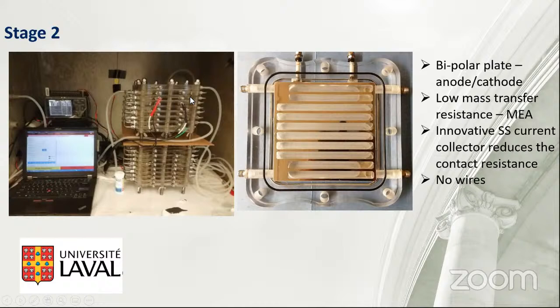This microbial fuel cell is basically inspired by the hydrogen fuel cell. It has a bipolar plate. This is a cathode, and the opposite side is an anode, or vice versa. And we developed again an 18-cell stack, similar to previous studies. But here we introduced a high surface area cathode as well. Using this microbial fuel cell, we achieved very high Coulombic efficiency, as well as COD removal of up to 80 to 95%, and we improved Coulombic efficiency from 35 to 69%. So that was almost double.